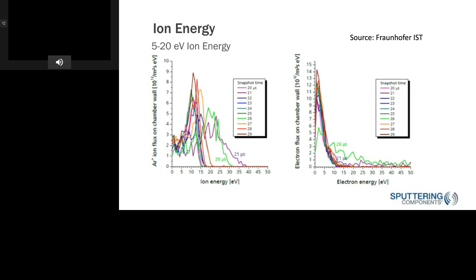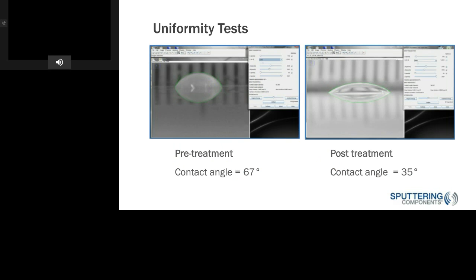efficiently. We looked at uniformity tests because when you're treating the substrate, you want to make sure that you're treating it uniformly, the whole substrate gets treated. So we did contact angle tests. You can see the picture on the left, the contact angle is 67 degrees, so the substrate is much more hydrophobic, and that was before pre-treatment. And then after treatment, the contact angle went down to 35 degrees.